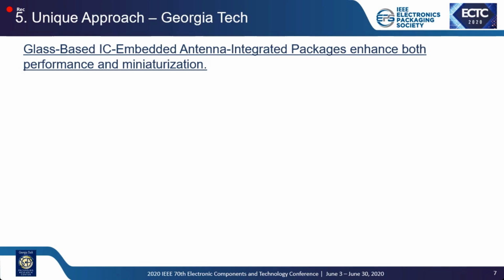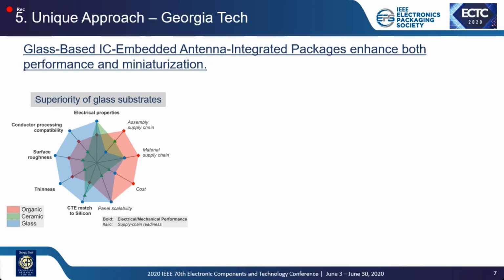And here is our unique approach. I know lots of people still ask us why glass. So I made a radar chart explaining the key properties of the three major substrate technologies. If you look at organic substrates, which are colored in red, we can still tell that the process maturity and supply chain readiness are obvious. However, the glass substrate is showing a superiority in electrical and mechanical properties, in addition to the metallization feasibility, thickness reduction, and dimensional stability.